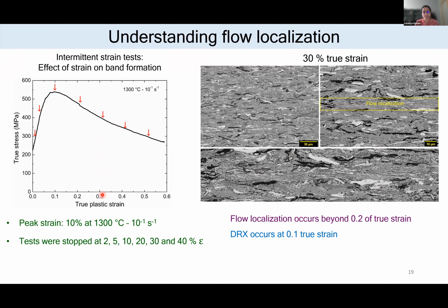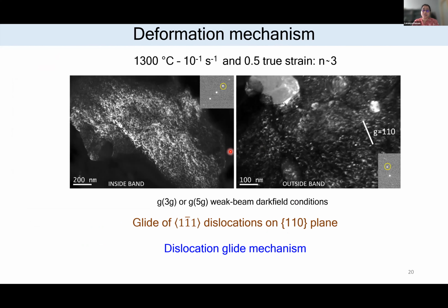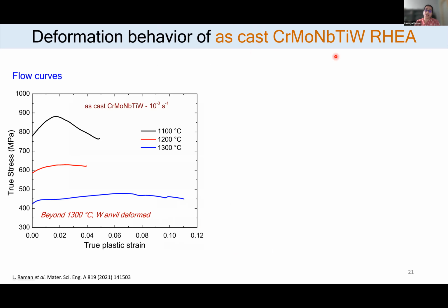And also what we observed from the dynamic recrystallization study is that DRX occurs at strains way ahead of this flow localization. Which means DRX happens first, followed by flow localization. So DRX is what is causing the flow localization in this alloy system. Now to confirm the deformation mechanism, we did some TEM analysis where we could see that inside the BCC grain, we have glide of 1/2<111> dislocations, which confirms the dislocation glide to be the active mechanism in the mechanically alloyed and sintered HEAs.